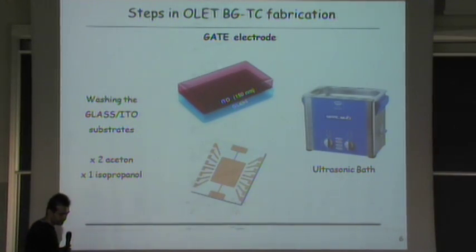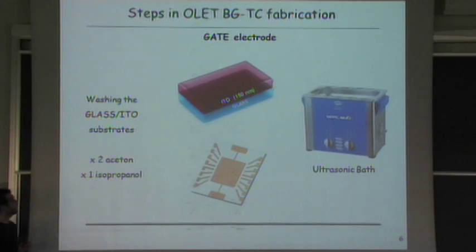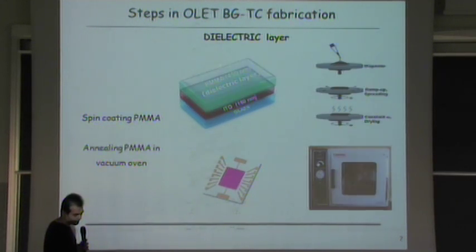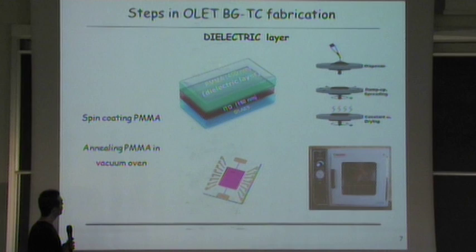Let's see in brief the fabrication steps. We buy the glass covered with a patterned ITO. So we wash the chip using an ultrasonic bath 2 times in acetone and 1 time in isopropanol. Then we spin coat the dielectric on top of the gate. Then we anneal it in a vacuum oven.